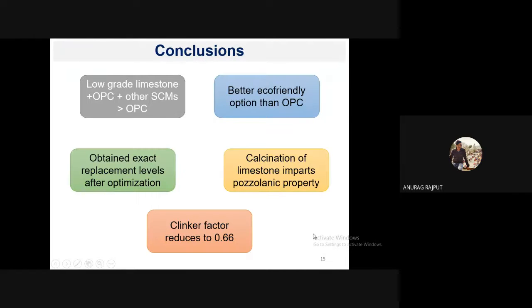So concluding this, if we use low grade limestone along with the OPC and other supplementary cementitious materials, we can enhance the properties as compared to the OPC. And this is a better eco-friendly option as compared to OPC, as I have told in the first slide. We obtained the exact replacement levels after the optimization, which can enhance all the properties. And calcination imparts the positive properties of limestone. And the clinker factor was reduced to 0.66, which is very beneficial.